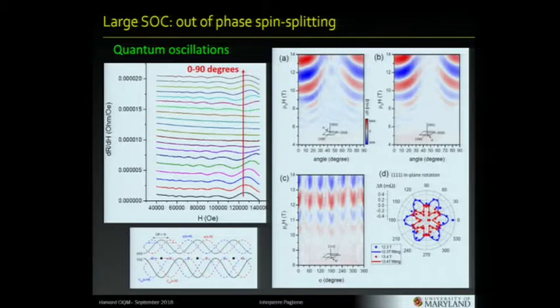Okay. Now this is unpublished work, but it's quite interesting. If you look at, and here's some raw data, if you look at the quantum oscillations in resistivity as a function of magnetic field, you can see the nice wiggles here. As you tune the angle, and this is basically going from like a principal axis 100 to 010, the equivalent axis, so sweeping through 110, for instance. This is a cubic system.